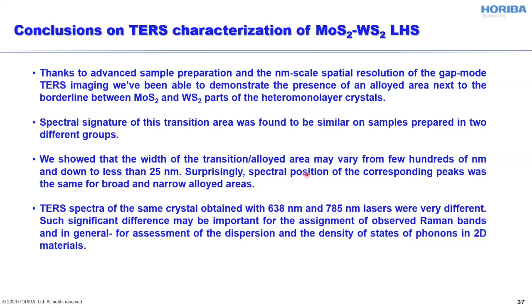And surprisingly, it looks like the composition of this transition area and the position of corresponding peaks in Raman spectra of this transition area is the same for broad and narrow lines. TERS spectra of the same crystal obtained with 638 and 785 nanometer lasers were quite significantly different. And such difference may be important for assignment of observed Raman bands and in general for assessment of the dispersion and the density of states of phonons in 2D materials.